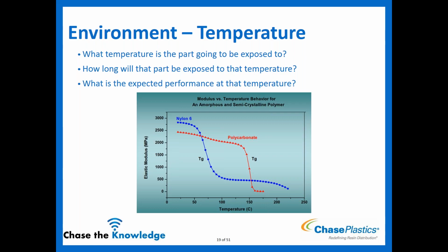So you might find that depending on what you're able to use as a performance indicator, maybe you're looking at 100 degrees C. Well, depending on what your requirement is for modulus, the polycarbonate is way outperforming your PA6. Maybe you can accept a huge loss in properties, but it still needs to hold something in that 200 range. Well, you can see that your nylon 6 now is starting to outperform the polycarbonate. So again, it's just one of those things where you have to understand what you're looking for specifically and what type of performance is required at that temperature.